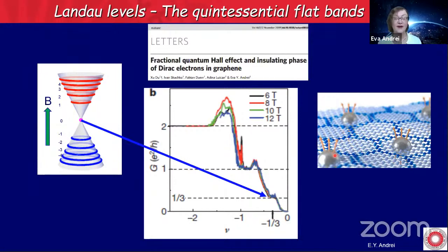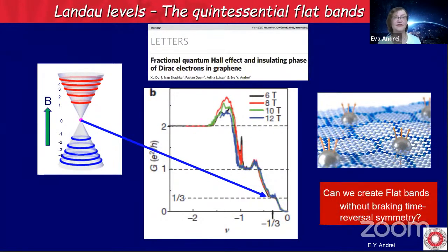And that is a signature of having created this new and correlated phase, which is very interesting in itself. However, the fact that we require a magnetic field to create these flat bands is problematic, because magnetic field and superconductivity are inimical to each other. So this doesn't help us much. If we want to achieve a room temperature superconductor or any other kind of phase, we would like to be able to create flat bands without breaking time reversal symmetry, which a magnetic field does. So can we do that? How can we create flat bands without breaking time reversal symmetry?